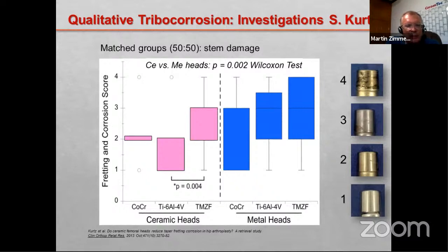This is now represented in this graphic with the axis 1 to 4. What you can see is two groups: on the pink side is the retrieval found with the ceramic ball heads, and the blue side with the cobalt chrome ball heads. If you look just at the average, you can see that the blue is higher than the pink one. So qualitatively, there was more fretting corrosion observed with metallic heads than ceramic heads.